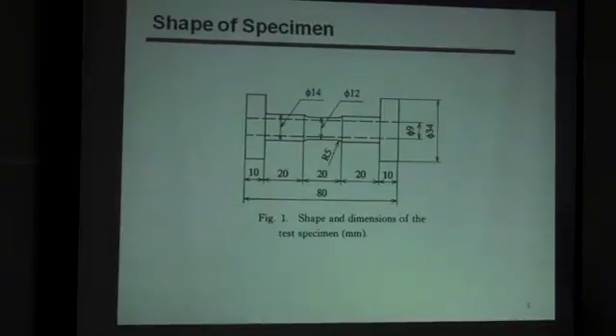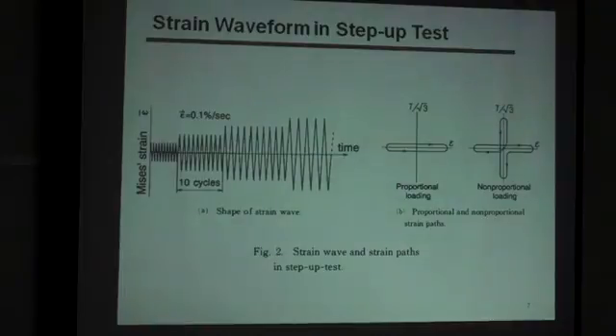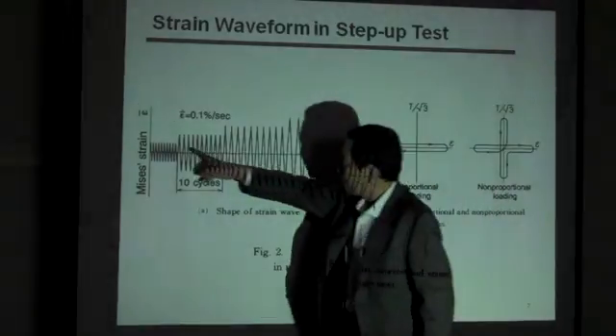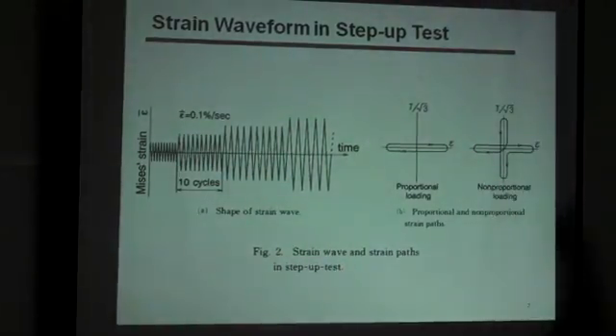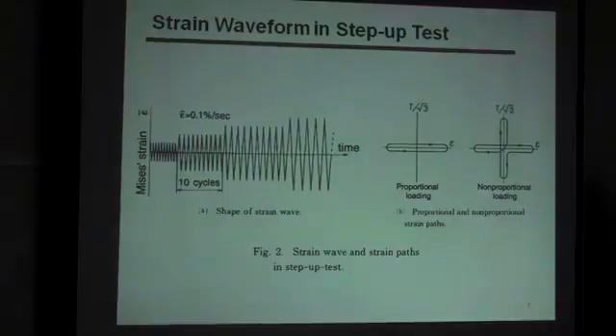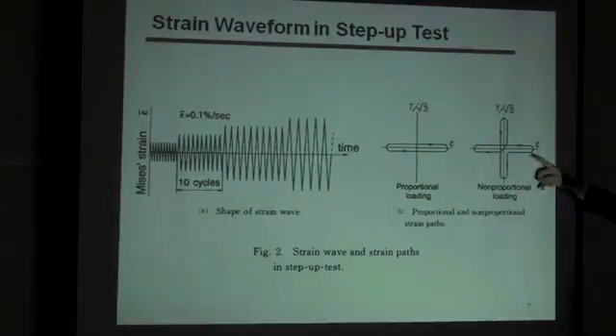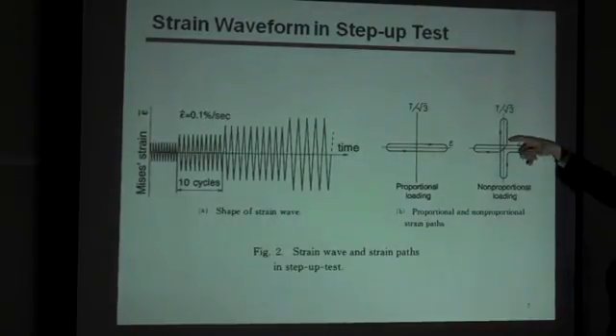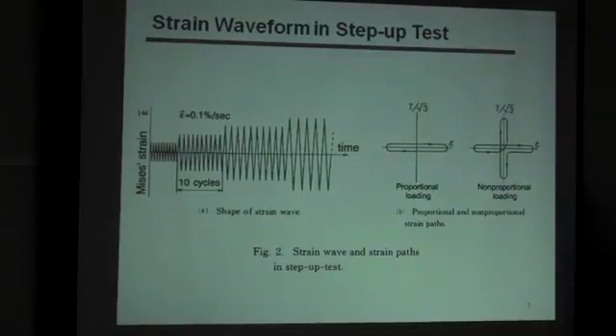And this is a specimen. We employed a tube specimen, and then we made a step-up test. So 10 cycles of constant strain amplitude and then increased. The stainless steel was strain hardening, and after the 10 cycles it saturated. And we got the stress response of the very last cycle, and we plotted the stress strain curve. This is the proportional loading, push pull. And this is the non-proportional loading: push pull, then the next is torsion, push pull, torsion. This is the corresponding loading.